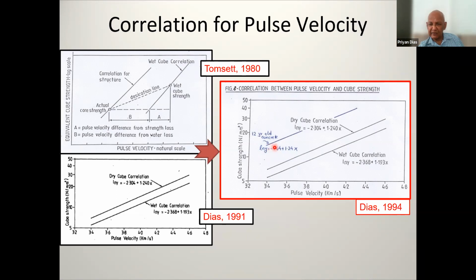And before taking each one of those cores, you measure the pulse velocity, right? So then when you crush those cores, you get a correlation between the strength and the pulse velocity. Once you have that correlation, you have tested only 12 places, both with pulse velocity and with core strength. But once you have this correlation, you can test 120 places in the structure using pulse velocity alone, just a probe like this on one side and the other side of an element. Once you get the pulse velocity, you can use this correlation to convert to strength. Right now,